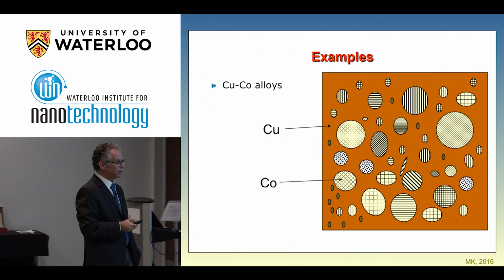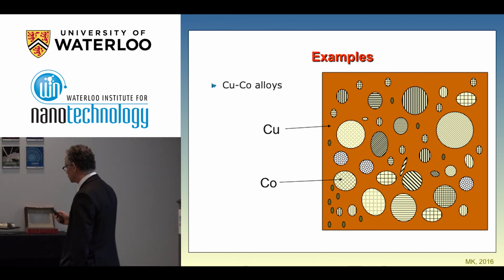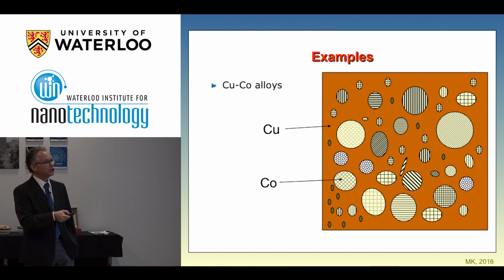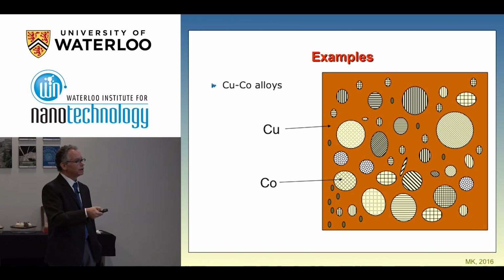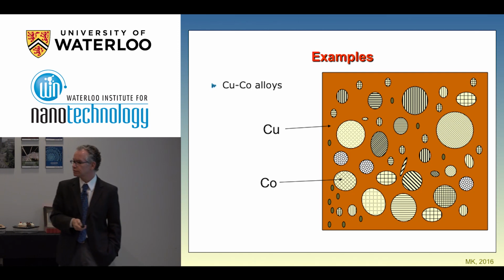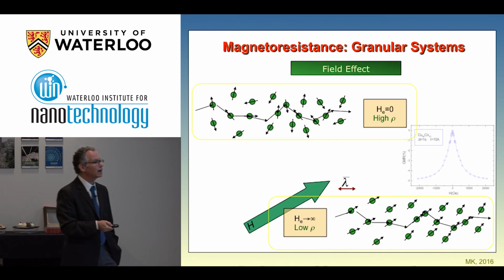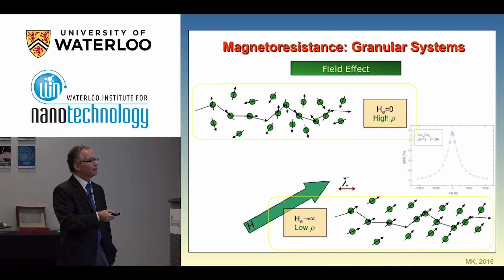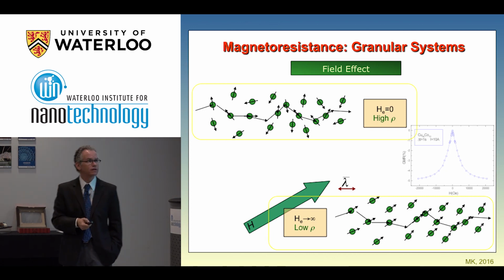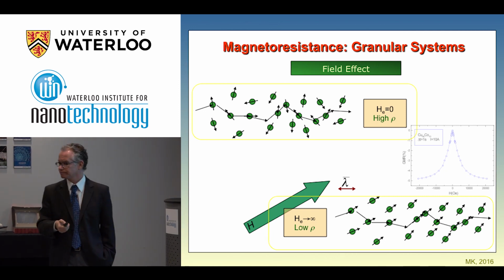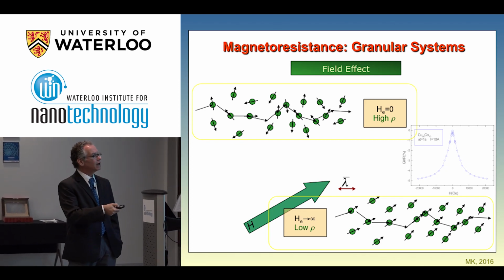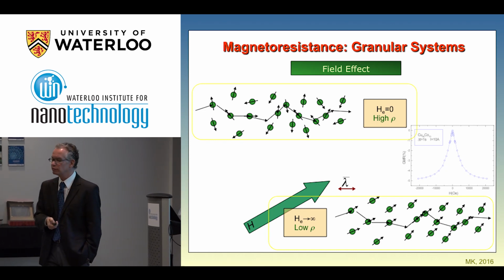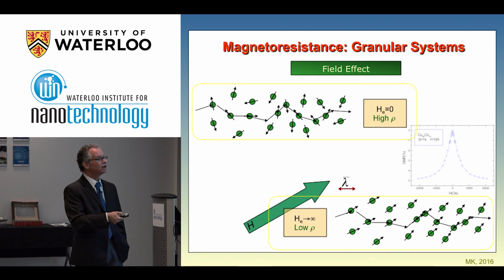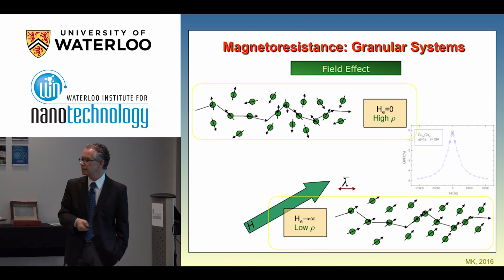Another interesting example is this kind of material, just to show you some interesting examples. Whenever you change your matrix and your nanocrystal, you can change completely the studies that you can make. So this is cobalt nanoparticles in a metallic matrix. This is copper. This indeed was the first system that I started studying. And in this case, whenever you apply a magnetic field in this kind of systems, you measure the conductivity or the resistivity of the system, you have a huge magnetoresistance effect. So the resistance of this system without field is completely different than the resistance of this system whenever you apply a magnetic field.